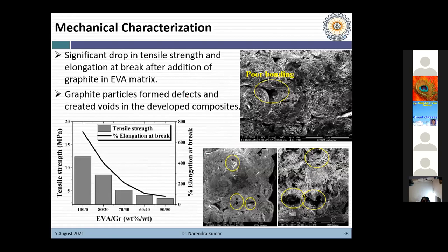Because we felt that the mechanical properties of the specimens had degraded, we took these SEM images for the broken samples. You can see poor bonding was there because viscosity was increased. That's why the poor bonding may be observed here. This is one raster, this is another raster. You can see these kind of holes were available within the specimens. These small holes were observed, right?